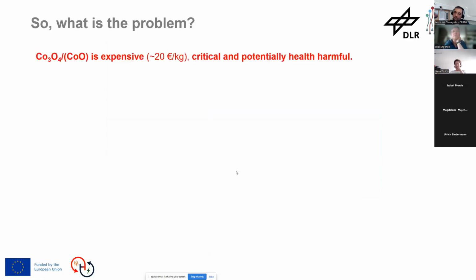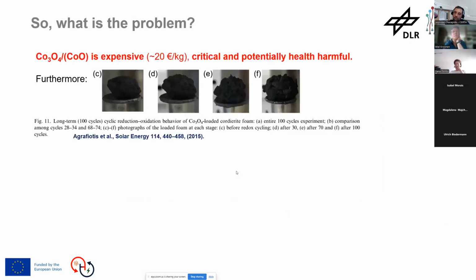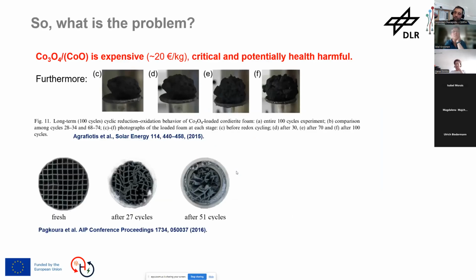The problem is, as we said before, that cobalt oxide is expensive, critical, and potentially harmful. And furthermore, it expands irreversibly upon prolonged cycling. Here you see, for instance, a honeycomb made of cobalt oxide by our partners at CERTH, which after 27 cycles, you can see that the structure collapses because the expansion is irreversible, and eventually the whole structure is useless.